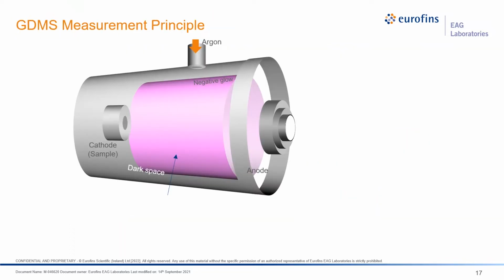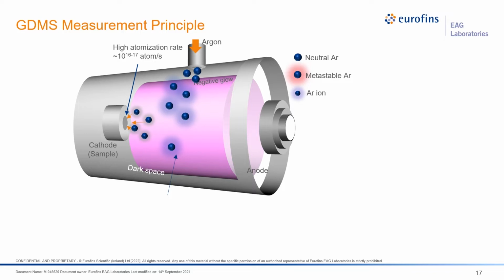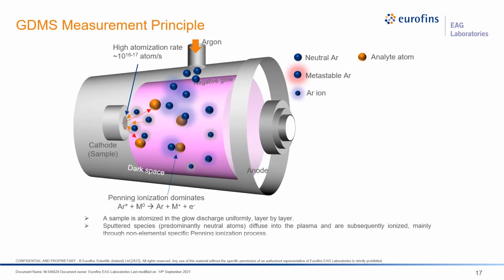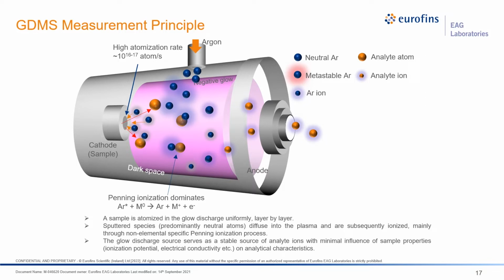Here are more specific details of the GDMS measurement principle. Argon atoms are introduced into the GD source with an established electric field. This starts forming plasma, and the plasma argon ions are accelerated toward the cathode, which is negatively biased. Those argon ions bombard the sample surface, causing its ejection into the plasma, where it is ionized predominantly by the Penning ionization process. The ions formed are then extracted to a high mass resolution analyzer such as a magnetic sector. The glow discharge source serves as a stable source of analyte ions with minimal influence of sample properties, including ionization potential, electric conductivity, etc., on any analytical characteristics.